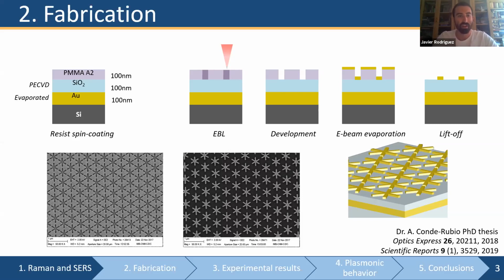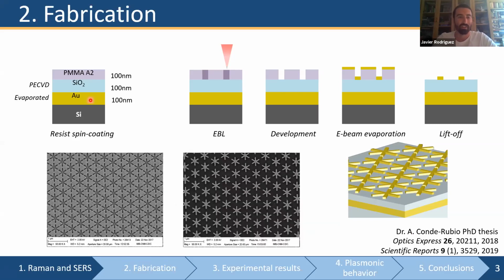Well, we just take a silicon wafer and we deposit several layers on top of it, which is just a continuous gold layer. On top of that, say a continuous silicon oxide layer, and then a resist on top of all this setup. This resist will be used in the process of fabrication through electron beam lithography. And by using an electron beam, we're going to draw the design pattern on that resist, and then that pattern will be etched. So the only thing that will be left is evaporating a thin film of gold on top of the system. And by a final step, which is called liftoff, we are going to get rid of the excess resist along with this fine layer of gold that in principle we are not interested in.